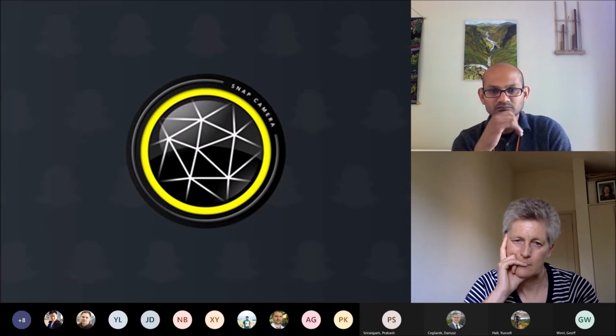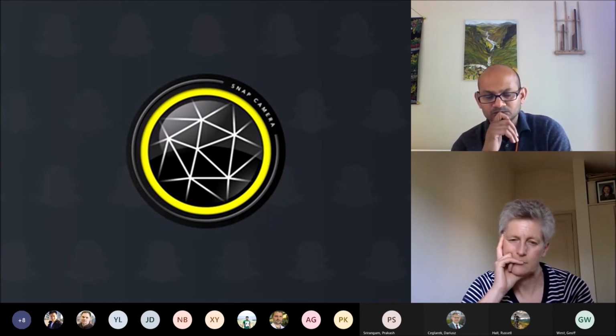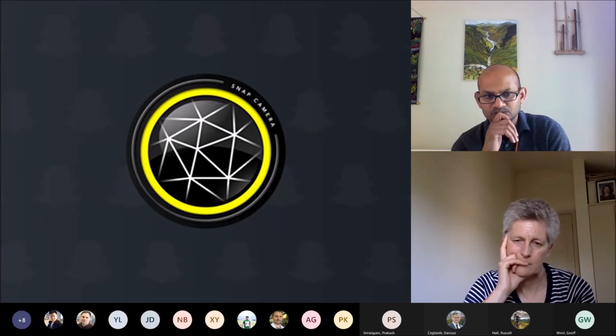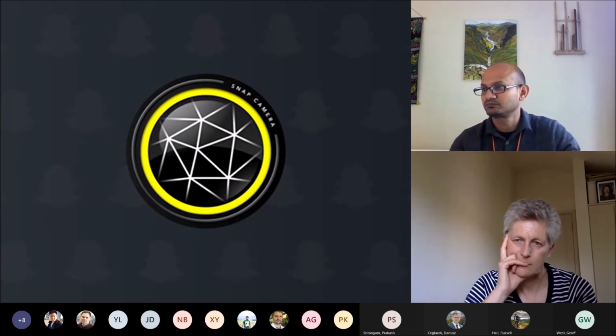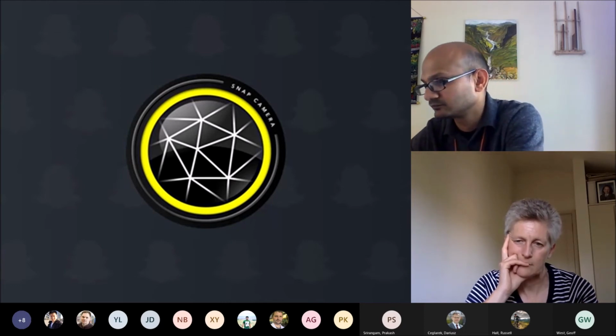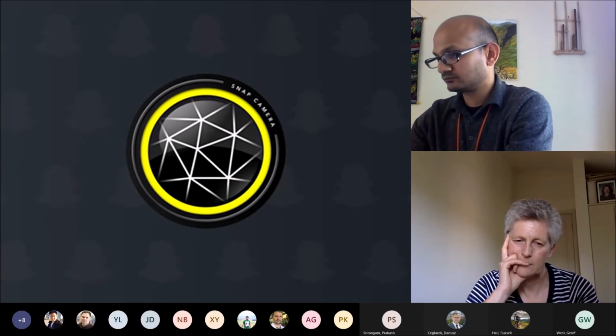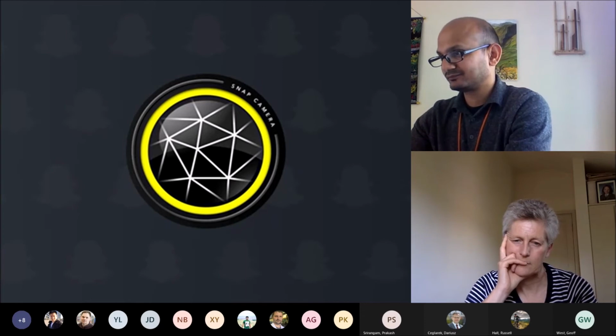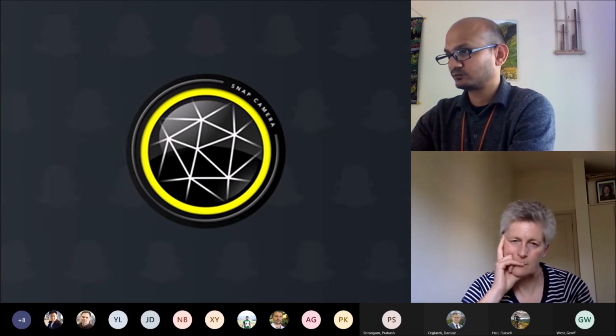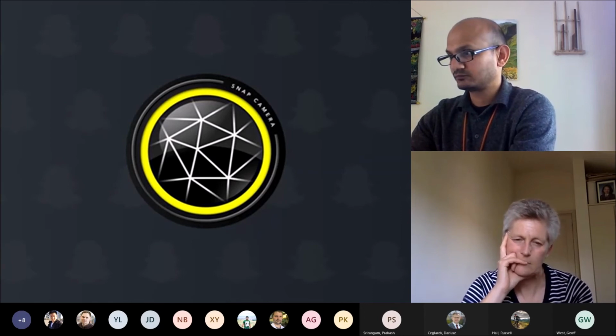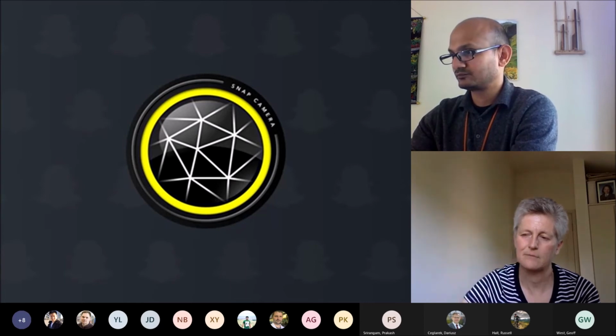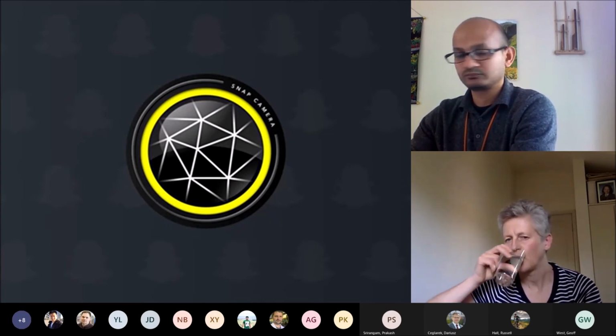But what we found out from our neutron diffraction data is that the unit cell is not cubical, that is, the unit cell is distorted, and that's helping at least one or two of the 110 to have very low symmetry. So this is not very high symmetry anymore by adding more silicon. And when you are occupying each of these, because they are substitutional, you are shrinking the unit cell. By having that, when you are having a suitable 1,1,0 to be expanded, and the heat flux, if you direct it in a way, it will help the thermal conductivity to reach the grain boundary for the Goss grain much better than the other orientation.